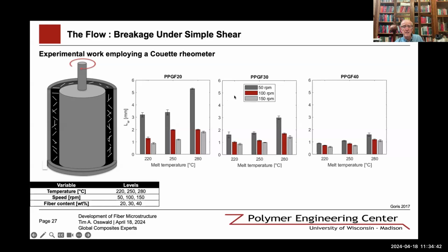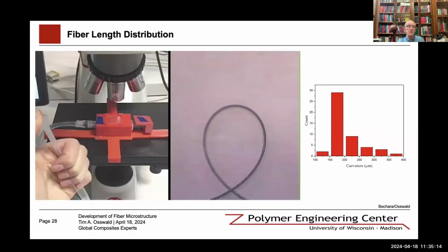But the other thing you can see, as we move to the graphs on the right-hand side with higher fiber content, is that you will have, of course, more fiber interaction, which we also see in the orientation models. And the higher the fiber interaction, the lower the length distribution. So all these things play a role, and there are models, of course, such as the one by Phelps and Tucker that uses a buckling effect.